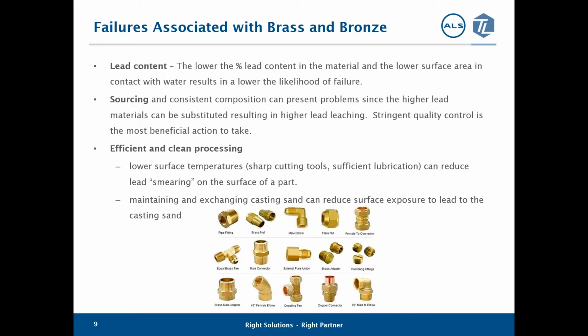Another thing manufacturers can do is to maintain a consistent supply chain. This means that manufacturers must maintain a quality supply chain which assures they are receiving the same low lead material that has been specified from their supplier. Thirdly, lead exposure can be reduced during the manufacture of alloys by keeping the processing temperatures low during the machining process and to change the casting sand on a regular basis to minimize lead contamination of their product.